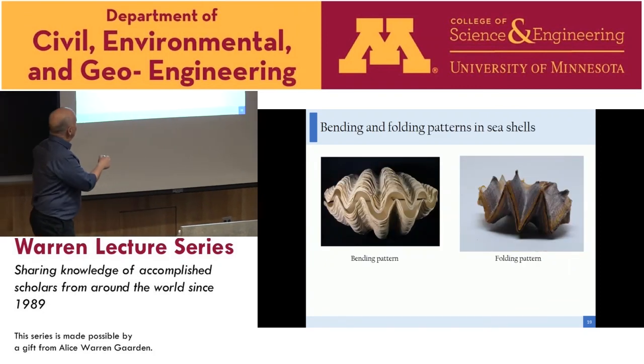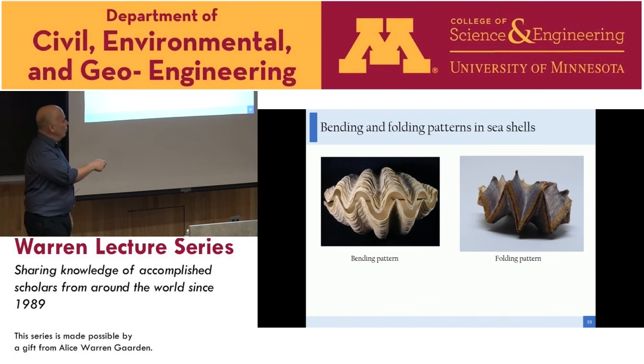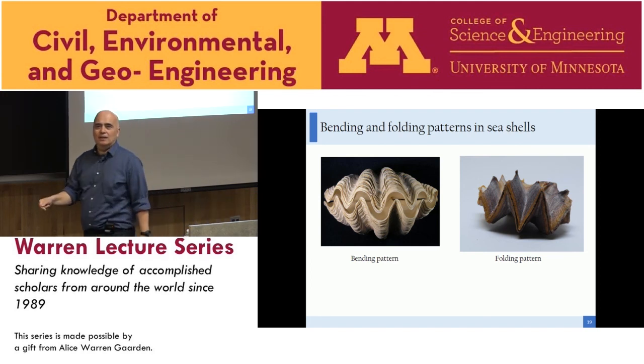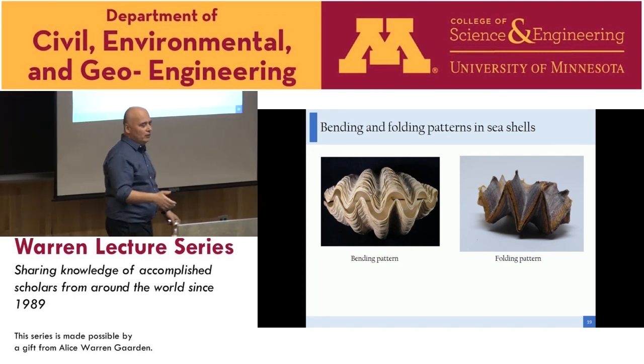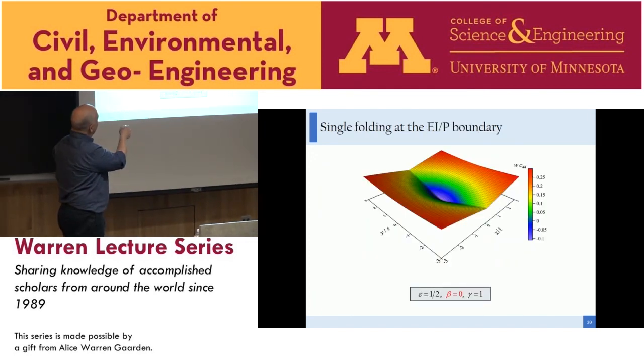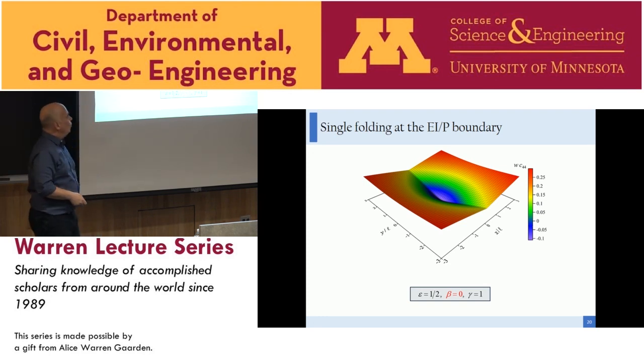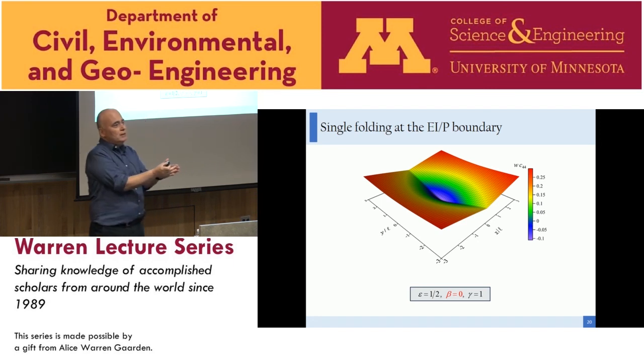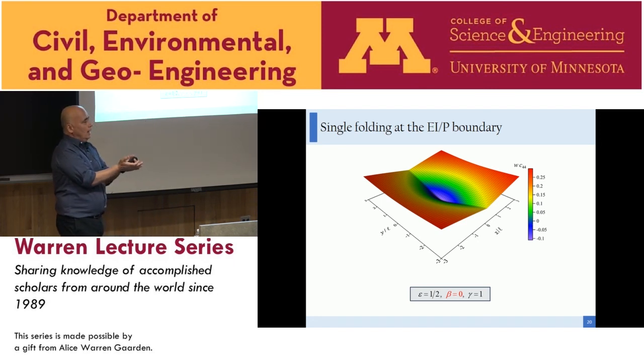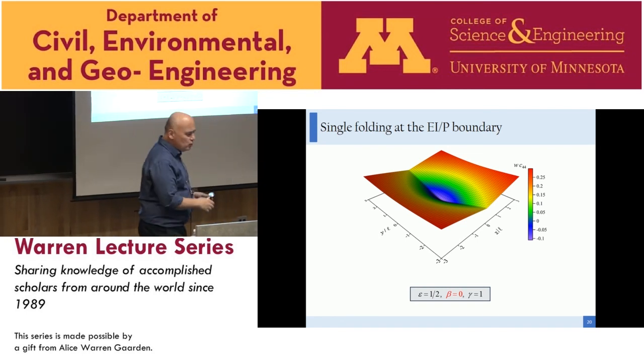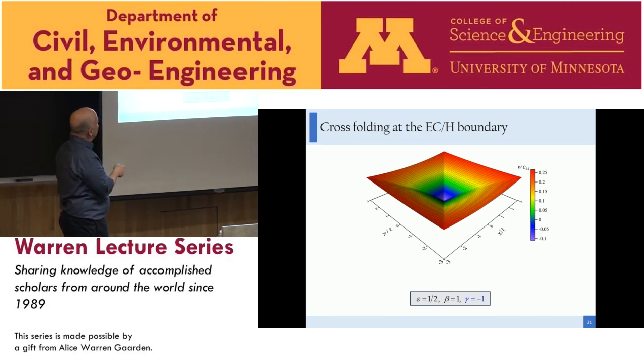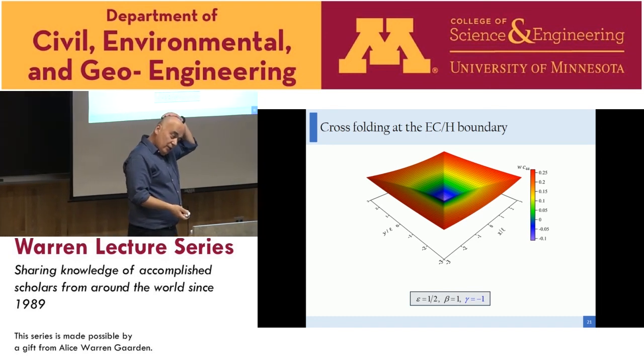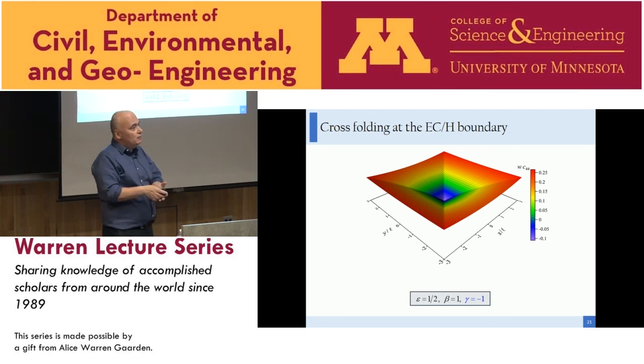Moving to our extreme constrained Cosserat material: when we perturb it near the boundary of ellipticity loss with a concentrated force near the elliptic-parabolic boundary, we see the clear formation of a fold. It can be formally proven that at the limit of ellipticity, the solution displays a discontinuity in curvature and a corner. Near the elliptic-hyperbolic boundary, we see the formation of a cross-shaped fold. This proves that folding can be related to the microstructure effect.